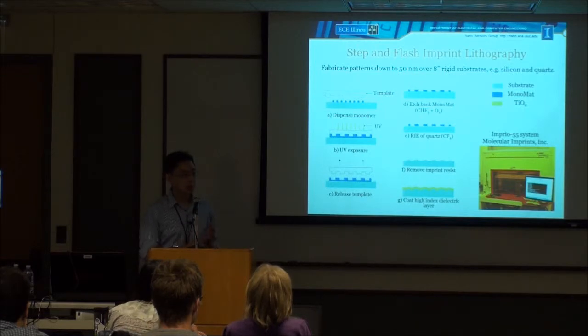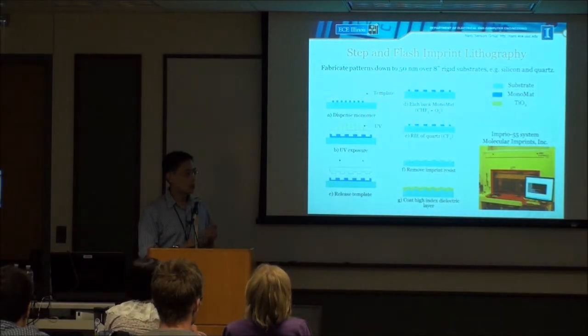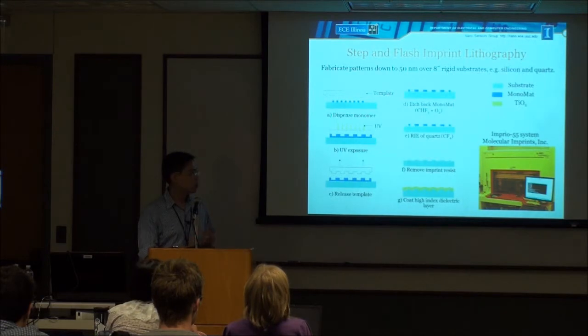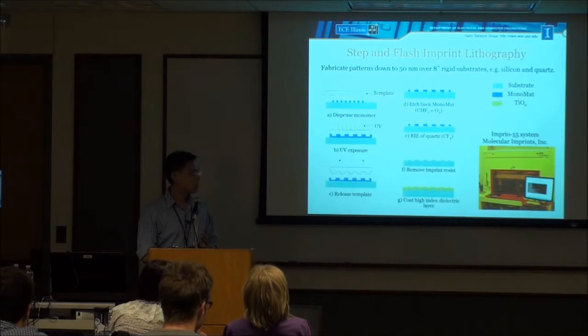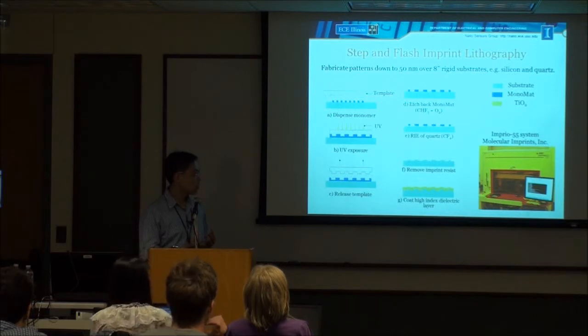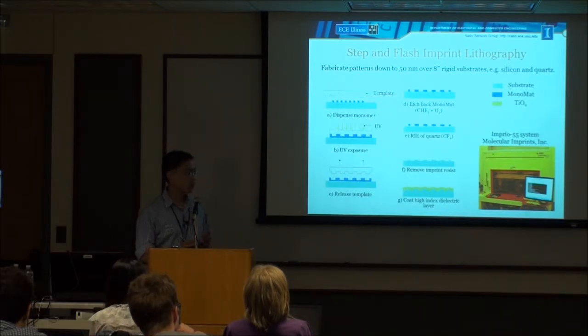You have to use a plastic substrate, which is flexible, and it also relies on UV cure epoxy. Both of them have a very high autofluorescence level. The autofluorescence is a background signal for fluorescence detection. It prevents you from seeing very low concentrations of fluorescence molecules.